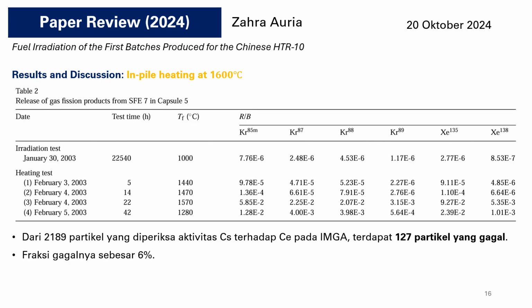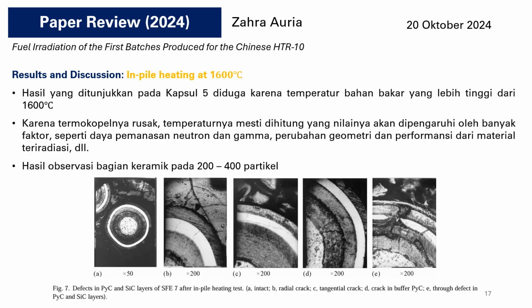This is the result for the release of gaseous fission product from sample 7 in capsule 5. From 2189 particles, there were 127 particles that failed, and the failure fraction was 6%. It is suspected that the fuel temperature in capsule 5 was actually higher than 1600 degrees Celsius. That's why the thermocouple was damaged, and the actual temperature must be calculated, but the calculation depends on many things like the neutron and gamma heating powers, the geometry changes, the performance of irradiated material, and so on.